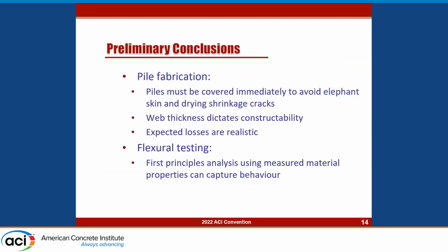So our preliminary conclusions at this point, on the pile fabrication side, piles have to be covered immediately in order to minimize those drying shrinkage cracks and to avoid that elephant skin. We also found that the web thickness is often what's going to dictate our constructability because we have to make sure that we can get around the strands in the web in order to fill up the forms. To that point, using an overhead bucket isn't quite ideal because there isn't a lot of head height to push the UHPC into the forms. So not recommended, but it did work for us.